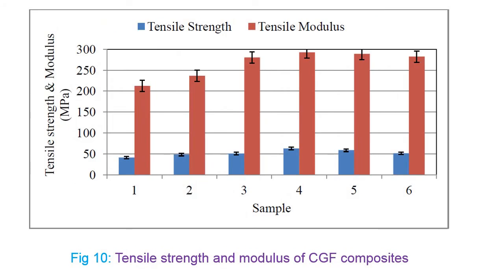And then when we are going for a tensile test, we will get tensile strength and tensile modulus. The tensile strength is in blue color, you can see, and varies from 41 megapascal to 58 megapascal. The tensile strength is the maximum load that a material can support without fracture when being stretched, divided by the original cross-sectional area of that material. We have to calculate it.